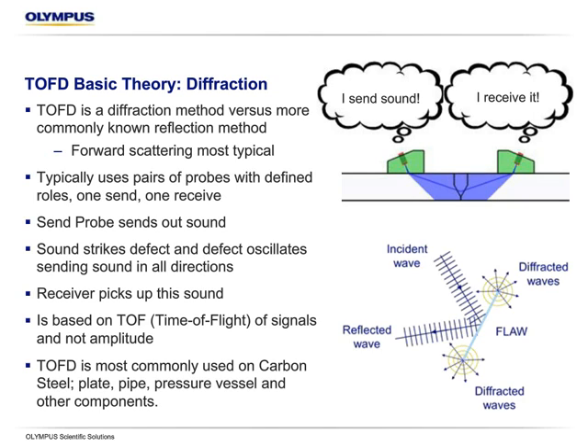TOFD is actually a diffraction method where we hit the flaw, we flood the area with a whole bunch of sound, and then the idea is that the space, the volume, whether it's a lack of fusion, whether it's a crack, something of a different density like a slag inclusion, we basically, at the particle level, that whole flaw will vibrate and send out a diffracted energy in all directions. So we're not really worried about the angle that hits it. Basically, we want to pick up all the different areas of diffracted energy from the flaw, and then we're going to use some techniques to measure and analyze that indication.